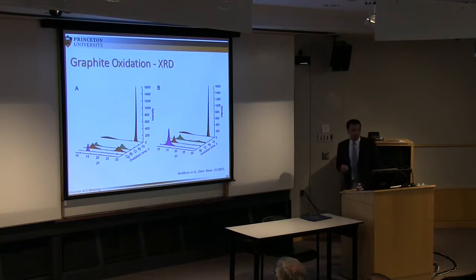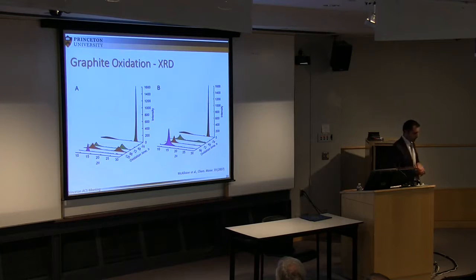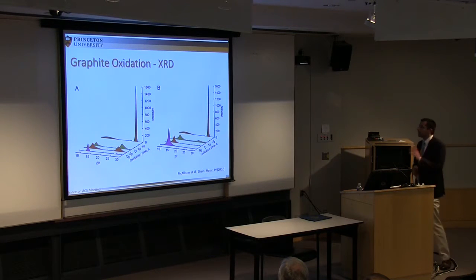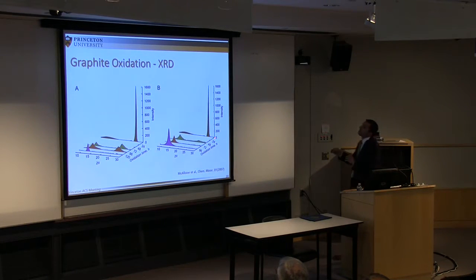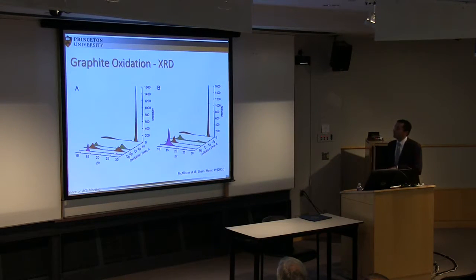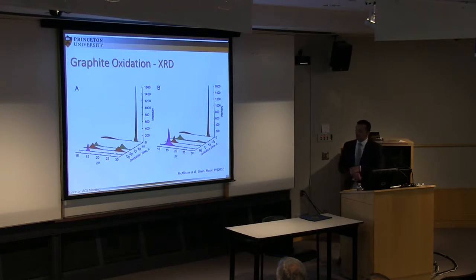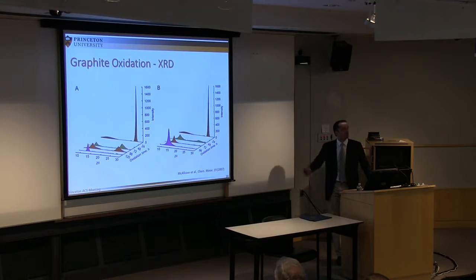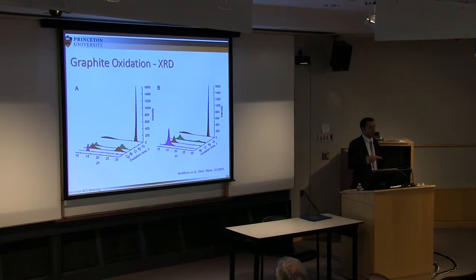But if you now use a smaller size graphite flake, after 48 hours, so you have already improved the yield, you start seeing the signature of graphite oxide, which is also an important parameter to consider. Of course, this is at the beginning, 2007. It has been further modified and improved.